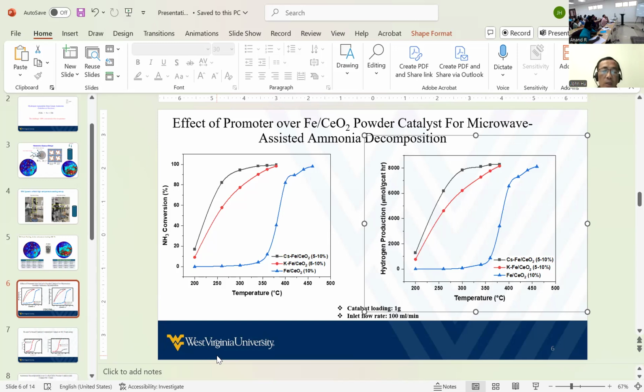I spent half an hour discussing a design concept on the monolithic. Now we're back to the active ingredient, which is iron on ceria, which eventually will be coated on the foam or monolithic structure. This is another way to design the catalyst. So we do the powder; it's called a screening test. This blue line shows the iron on ceria without promoter. If you have a potassium promoter, then they basically go this way.